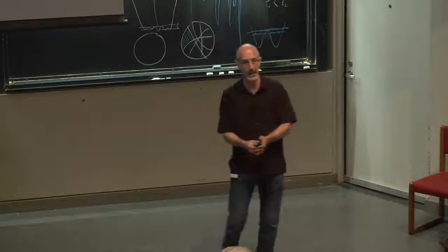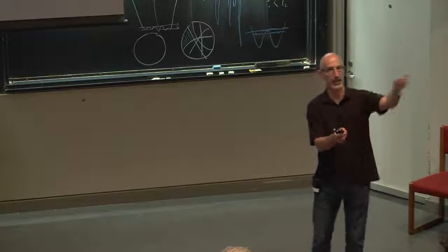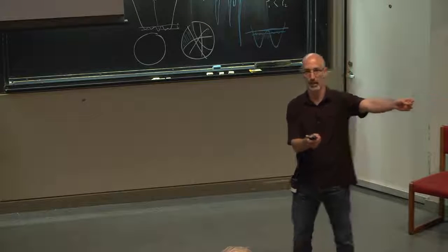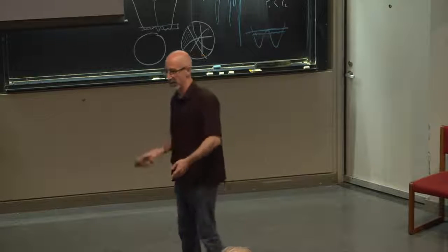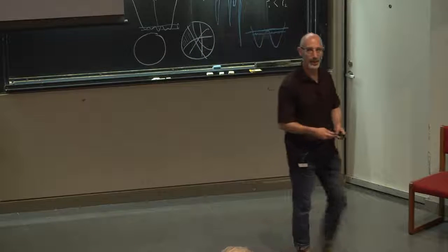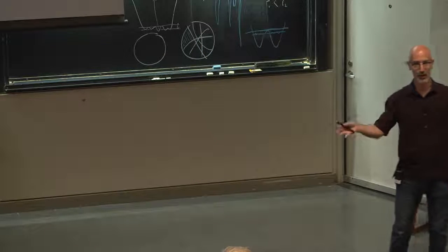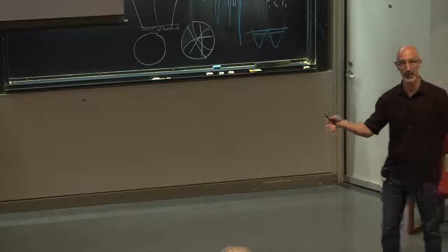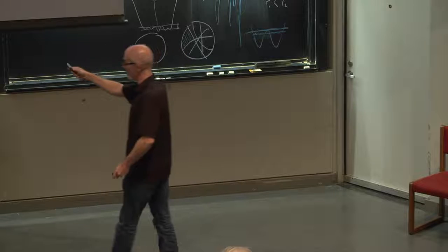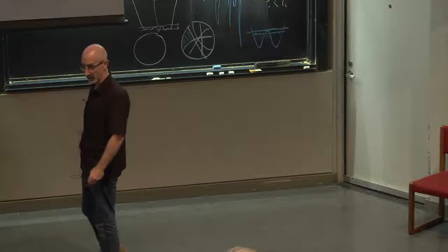So what this is saying is the probability of making a very large displacement is much more probable than you would expect from just your standard Brownian motion type picture. Now, it's always going to be true, even at relatively high temperatures, that if you go to far enough displacements, the central limit theorem doesn't work. So nothing says that there has to be a Gaussian distribution for arbitrarily large displacements.